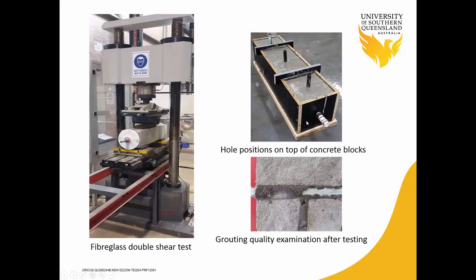This picture shows the mold that was recently made in the Centre for Future Materials at the University of Southern Queensland for casting concrete blocks. These are used to make the hole on top of the sample, and this is the rod, and you can see the wire around it to make the imprint of the rifling. Once the sample is cast, the fiberglass is positioned inside the concrete block, and the whole assembly is positioned inside the compression testing machine, and the middle block is subjected to compression at a predetermined rate of around 2 mm per minute. The shear load against shear displacement is measured.